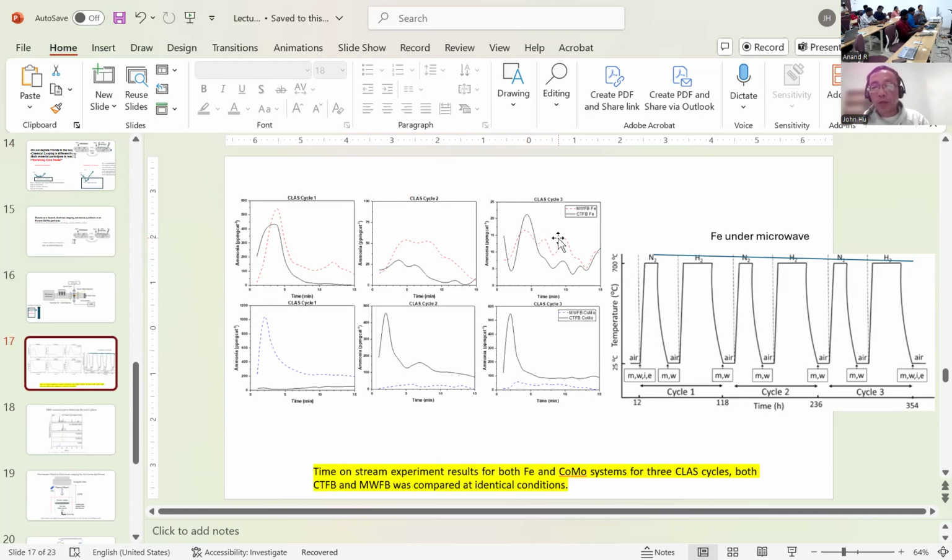You want to see maybe 1 or 2 peaks, then stop, and go to the next cycle. Otherwise, it's very difficult repeating. But in terms of quantity of ammonia, the quantity has nothing to do with the peaks. It's related to the area underneath. So if you integrate the area underneath this red line, it's about the same. It's just the steps of how you produce the ammonia that are different, because it's getting more and more difficult. The more peaks, the more difficult.